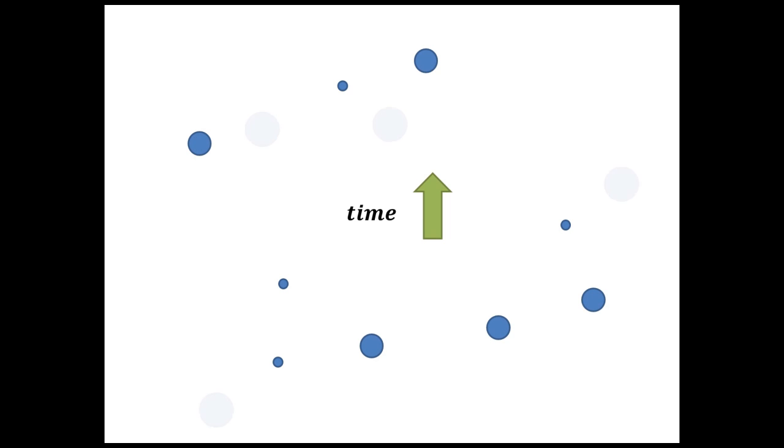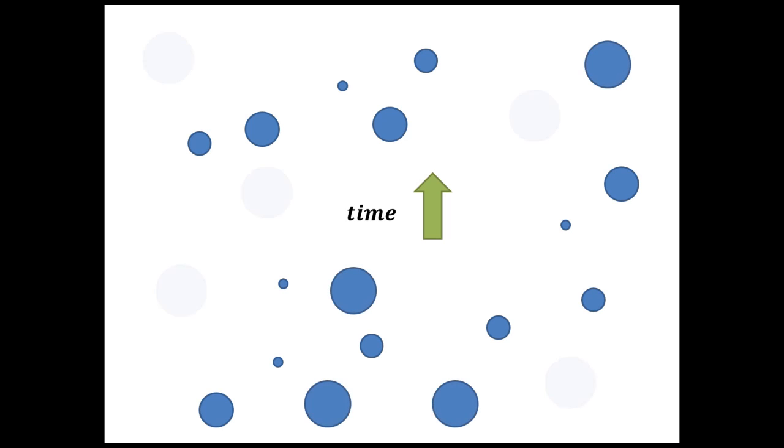During polynuclear growth, which occurs when the surface concentration is very high, surface process is so fast that second layer growth proceeds before the first layer growth is complete. The growth rate of particles is independent of particle size or time. That is, the growth rate is constant, where Kp is a constant only dependent on temperature. Hence, the particles grow linearly with time.